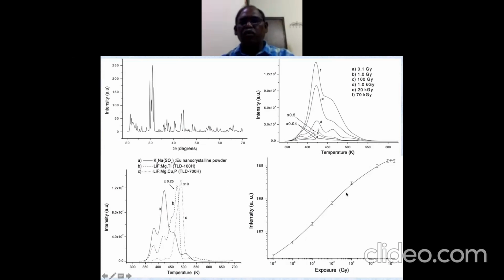Generally, this we have also studied in microcrystalline, so it saturates around maybe 100, 150 gray. But here you can see that this doesn't saturate even up to 10⁵. This is around 10⁵ gray. And therefore, this has applications for measuring such kind of very, very high doses.